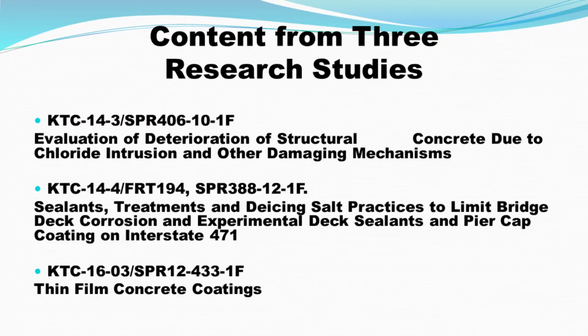The first report, the evaluation of deterioration of structural concrete due to chloride intrusion and other damaging mechanisms: the Kentucky Transportation Cabinet looked at a lot of bridges and saw a lot of concrete deterioration, not so much at beam ends, but at pier caps and abutment seats. And so they commissioned research to look at a number of bridges and identify the chloride ion levels at pretty much mat depth, about 2 inches into the concrete surfaces.